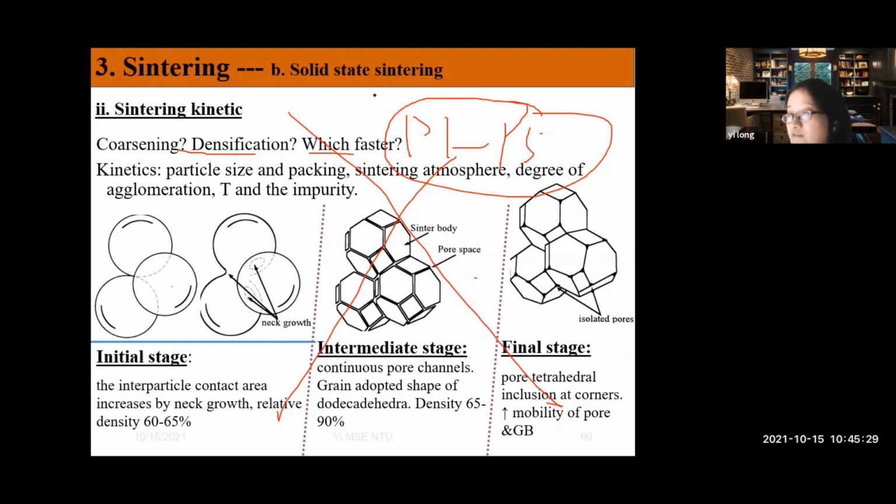You ask a very good question. So there will be an increase in surface diffusion, right? Not necessarily. Surface diffusion needs lower temperature to happen, but P4 and P5 need higher temperature to happen. As I said, P1, 2, 3, 4, 5 happen all the time. So that's why we need to calculate the rate. I'm not saying that when P4 and P5 happen, P1 is not happening. Actually, everything is happening at the same time.